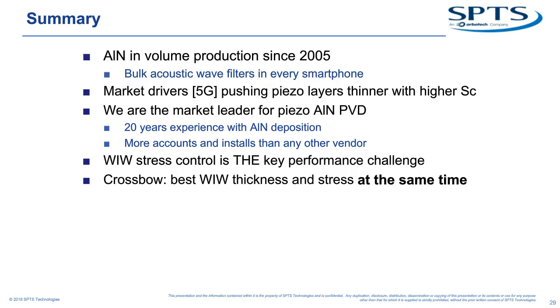So my summary slide then, aluminum nitride has been in volume production for 13 years now. They are in every smartphone. They increase every time the wave bands expand. 5G is going to be pushing layers to go thinner, and we're introducing scandium content into those layers. We are the leaders in aluminum nitride. We've been doing it for more than 20 years. Getting stress control and thickness control is the key challenge, and we are the only company who can provide that at the same time. Stress uniformity is far better than any of the competition.